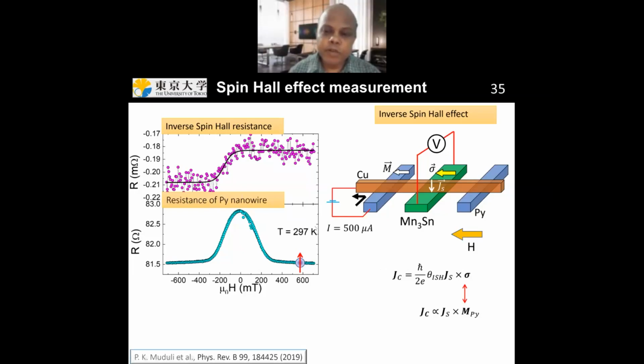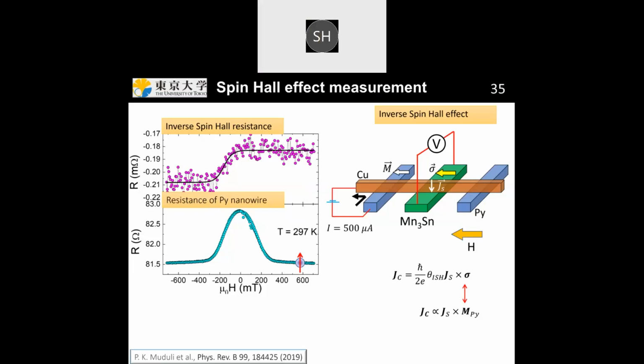This is because this material supports some spin accumulation in other directions. One expects some spin accumulation which is perpendicular to the surface. So there is some other mechanism present, and we call it the magnetic spin Hall effect. That is why the signal is shifted. So it is possible to see this kind of effect in this data also. That's why I asked the question, because the spin Hall angle can be quite large in one direction and very small in another, and in your case you have just 5%. I was wondering if you have maybe more than 10% or 20% in one direction. That would be interesting to know.